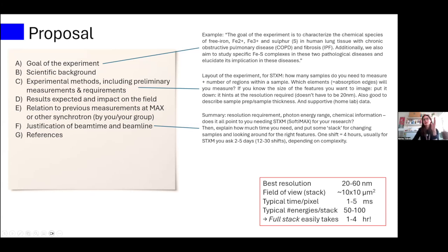The typical number of energies that you do per stack, if you do over an X-ray energy edge, can be 50 to 100. And therefore, if you do a full stack on one area on your sample, that could easily take between 1 and 4 hours if you do some averaging. So that would mean that one area, one edge on one sample will take you somewhere between 1 and 4 hours. And that is already one shift, right, if you take the upper limit. So put together a reasonable guesstimate of what you will need, and put in a little bit of slack, because you might want to change samples, and looking around on your sample to find the right feature, plus the alignment and so on, takes a little bit of time as well.